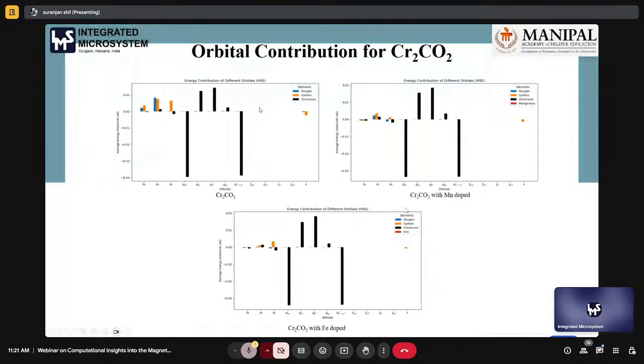Now we come to the analysis of orbital contribution for the magnetic behavior. What we see here, without doping, is that dxy and dx square minus y square mostly have a negative contribution in the energies. But if we dope with manganese, what happens? This value here you can see is 0.04, minus 0.04. Here is around minus 0.03. That is, it increases in the positive direction. That means it goes less stabilized.